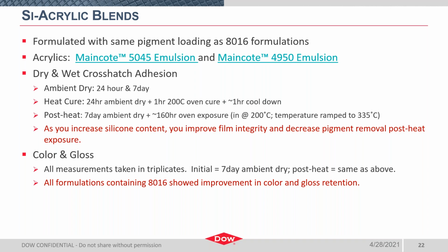And then your traditional silicone heat cure cycle of 200 C for an hour, and after high temperature exposure at 325 C for approximately 1 week. In addition to the adhesion, color and gloss measurements were also taken in triplicate, pre and post heat exposure. I'll summarize our findings before I share the raw data for adhesion, color, and gloss.